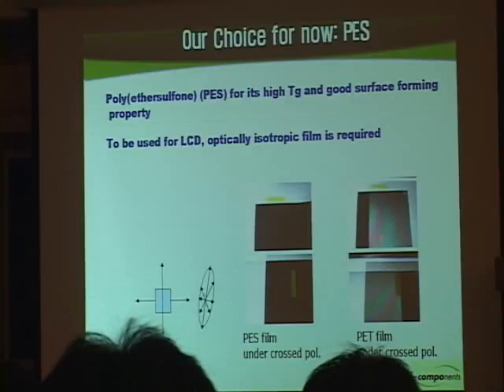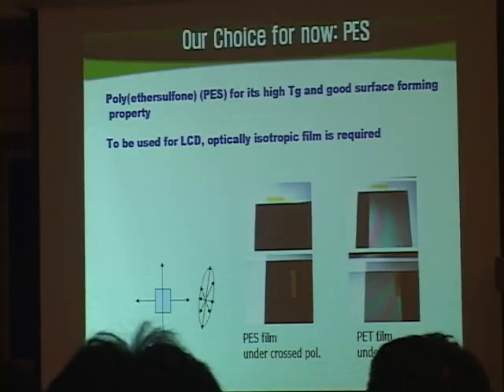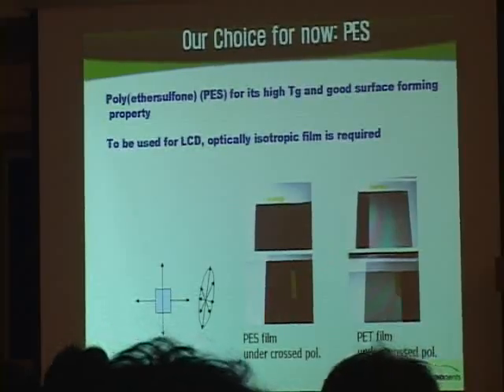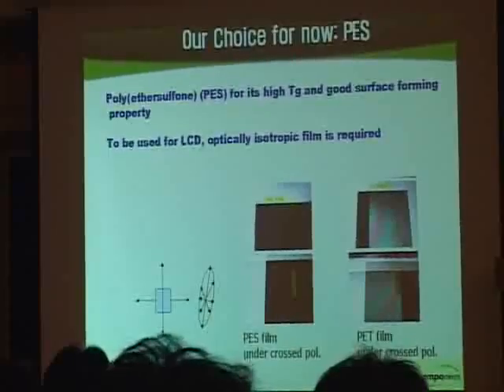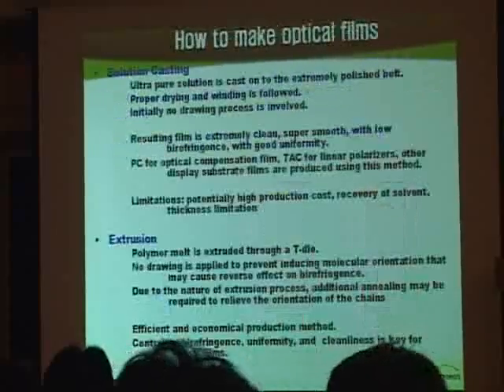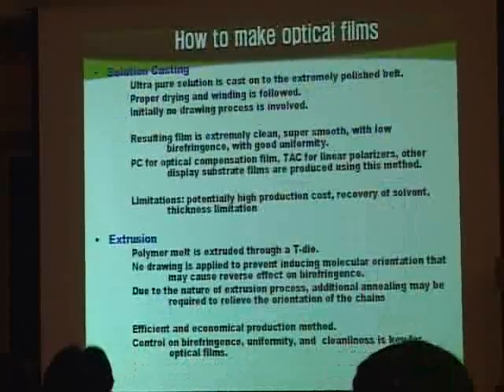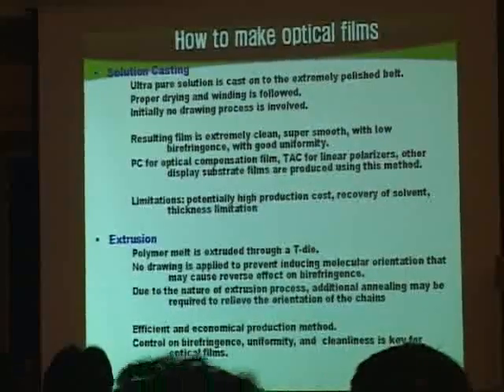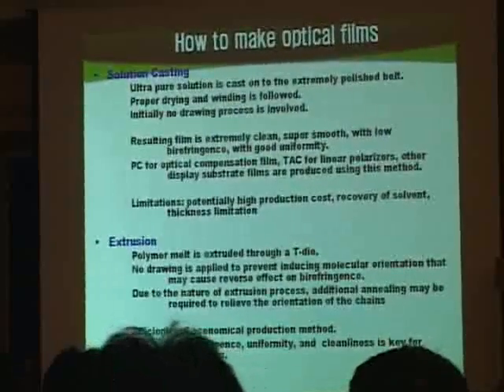For example, when we use a PET film on the cross-polarized setting, we see a lot of patterns due to the drawing of a PET film during its manufacturing. Then for the PES film we developed, as you see, this is pretty much isotropic. And then interestingly enough, there are two different types of methods to make optically isotropic films.